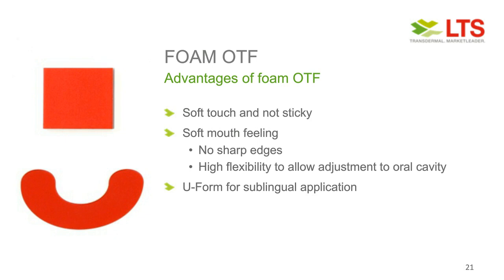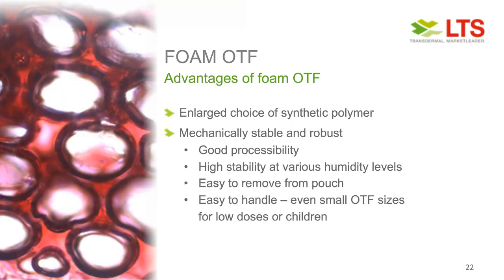Looking at the formulation and the processing, due to this foam OTF, as you can see here on the left in the picture, we increase the surface area of the film significantly by creating these foams. And this allows us within the formulation to use a much broader choice and variability of polymers. These polymer films usually would take significantly longer to dissolve and disintegrate, several minutes. And by creating the foam OTF out of it, we can bring these dissolution or disintegration times down to less than 10 seconds.